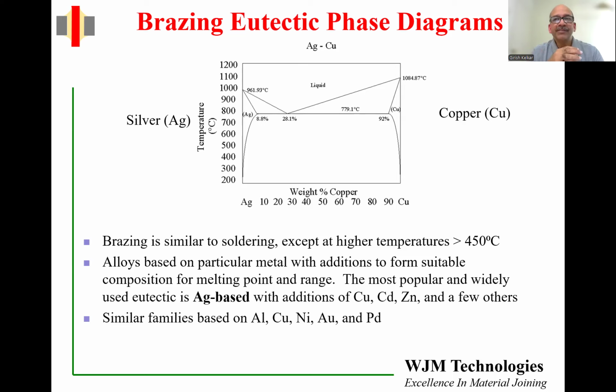Brazing is similar. Brazing is often based on a eutectic phase diagram. Here I'm showing you a eutectic phase diagram between silver and copper. Again, we have melting point on the vertical axis, and silver's melting point is 961. Copper's melting point on the right is 1084. And the mixture of silver and copper at 28.1% copper actually melts at a much lower temperature of 780 degrees centigrade. So you will find alloys based on a particular metal with additions of suitable composition. This is the basis of the silver-based brazing alloys.